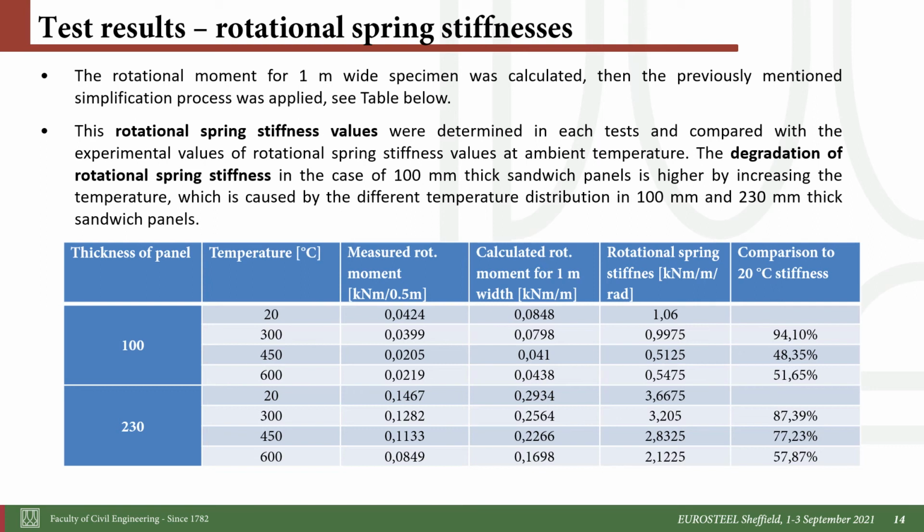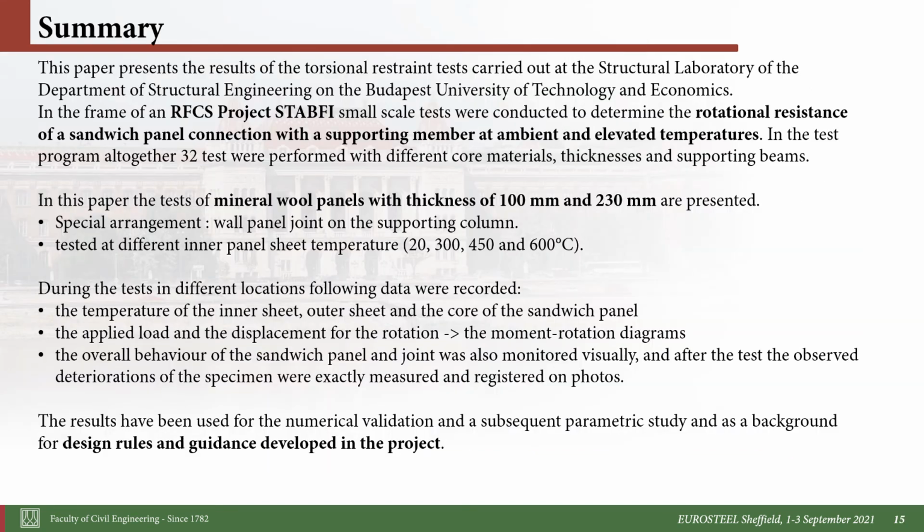You can see the actual spring stiffness values in the tables, and in the last column you can see the degradation of this kind of stiffness at different temperature values, and for these two kinds of panels what we used for the test value.